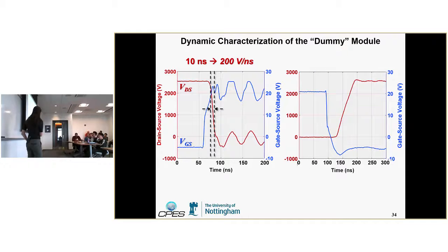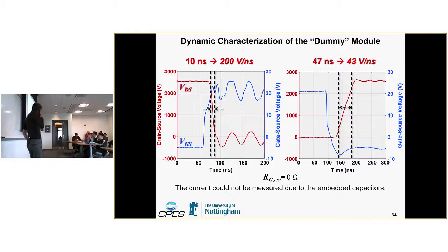And this is the turn-off waveform. This one's a little bit slower, about 43 volts per nanosecond. Still substantial. You're still switching kilovolts in about 50 nanoseconds. And this is all with 0 ohms external gate resistance. There's very little voltage overshoot. I think it was about 3% voltage overshoot, or 2%.